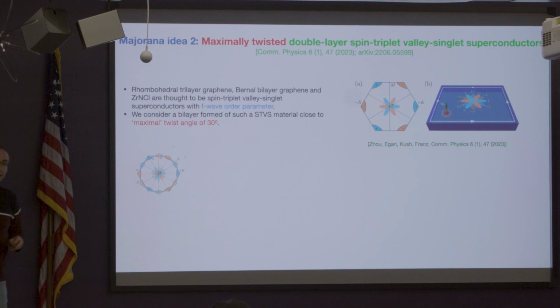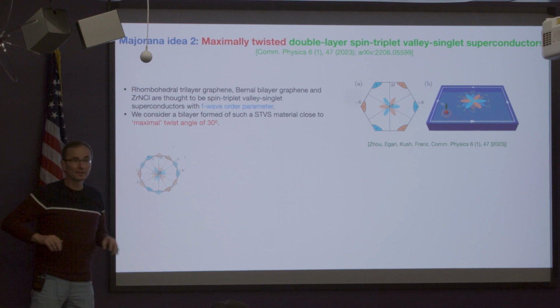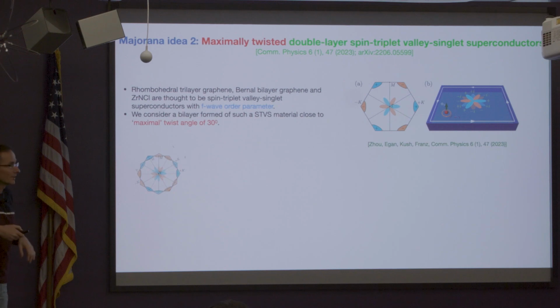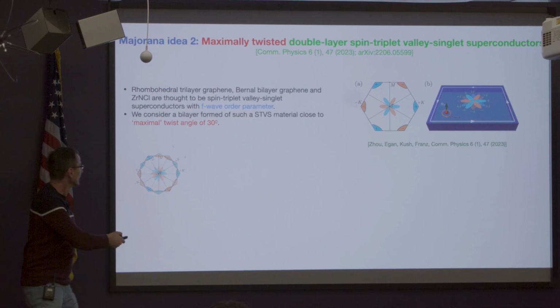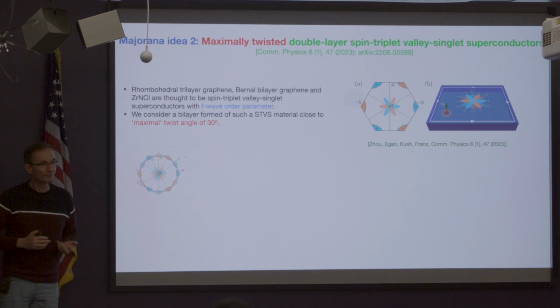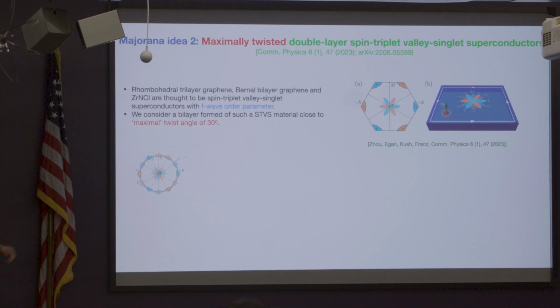Or it can take advantage of the fact that, in principle, this order parameter is a complex quantity, so it can go through imaginary values and form some complex combination of the two. And that would be an interesting situation. Just like in the case of twisted cuprate, where we argued we get a D plus iD, here we could get F plus iF, and that would actually break the spinless time reversal symmetry of this original system and could potentially be topological.